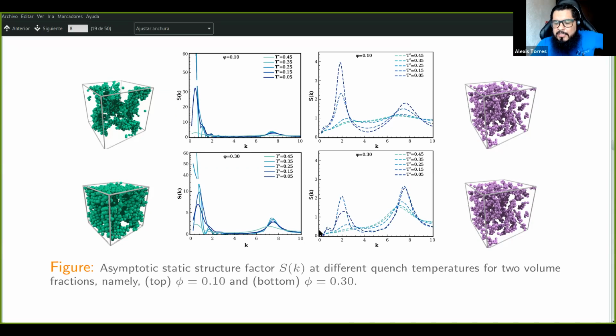Here, these first peaks, I can assume that is due to some kind of finite size effects. I cannot be sure if this is a real effect or something related with finite size effect due to the simulation limitation. But it's important to mention that the second and third peaks have almost the same magnitude. So in this case, we can assume that there are two characteristic lengths in the system.